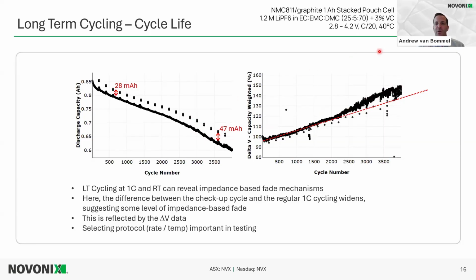And this is why we choose sometimes, if we want to probe impedance-based fade more, a 1C rate at room temperature at 25 degrees. If we want to just look at time-based fade, then we do C/3, maybe at an elevated temperature like 40 degrees for testing. So it's important to look at that rate and the temperature of testing.